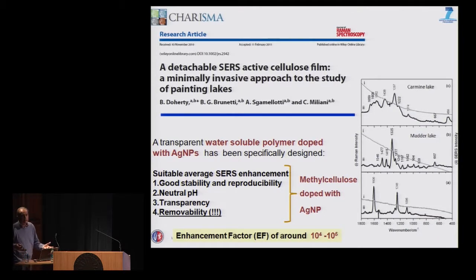The intensity of the signal is lower, but if you have patience and time, at the end the signal comes out. Another possibility to improve the signal in situ, to characterize organic substances, lakes for example, is to use the SERS approach. The idea here is to use a gel of methyl cellulose that has silver nanoparticles inside. You can put a drop of this gel on the surface of the painting, and then you carry out the measurements through the drop.